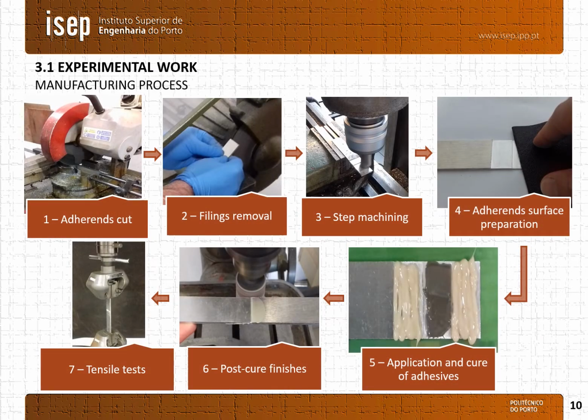In this slide are shown the manufacturing process stages of the adhesive joints. The adherends are cut, then the filings or the excess material is removed. After, we machine the steps and perform the adherend surface preparation. After, we do the application and cure of the adhesives, then some post-cure finishes, and then the tensile test.